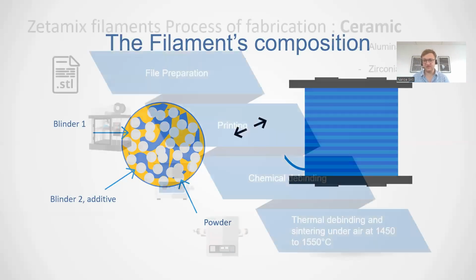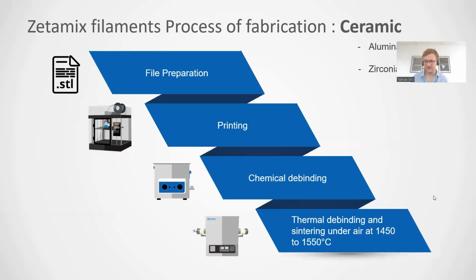The process is quite simple: we print the part using any standard printer. We then remove the binder by dipping the part in a solvent, and then fire the part, sinter it, put it in a high temperature furnace if you prefer, to get to a dense ceramic or metal. So with the technical ceramics, which is what we used to have, most of our technical ceramics will sinter under air, but at very high temperatures between 1450 and 1550 degrees Celsius. That's one of the limitations we wanted to break with our new material. We wanted to be lower in temperature, and maybe I'll explain a bit why later on.